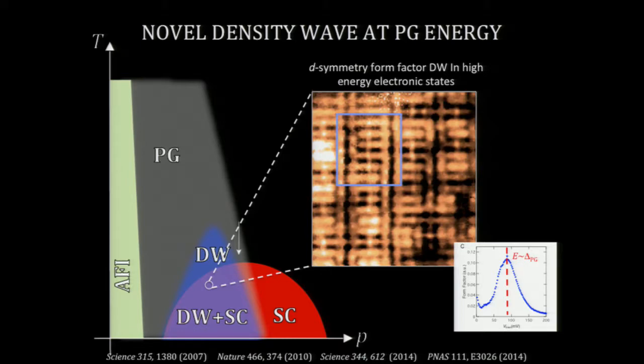My own work was to look at the density wave as seen by STM at a particular energy scale. STM can measure the electronic structure at any particular energy. And when we looked at energies which were related to this pseudogap, we found this very peculiar ladder-like structure. Actually, this observation was made well before I got to the scene. I started to do the analysis on this to see if there's actually any additional structure that we didn't know about before.